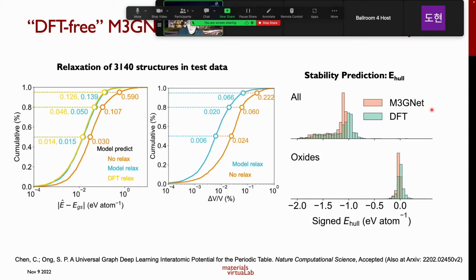With the energy predictions, we can also make stability predictions. We can calculate the stability of hypothetical crystal structures that we generate, and we chose the top 1,000 to compare with DFT calculations. We can show that in general, the distribution of the predicted E above hull is very similar between our M3GNet predictions and our DFT predictions.